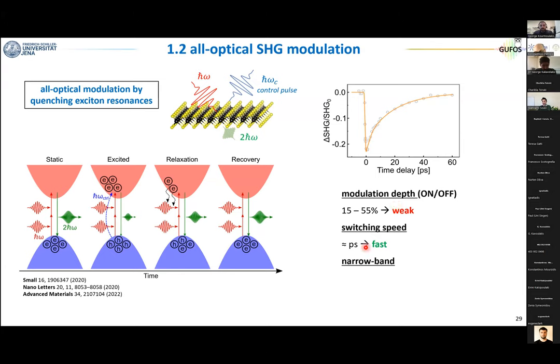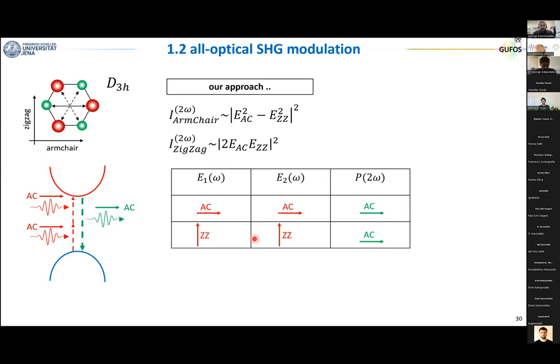But there is another big disadvantage, that this method is now very narrow band. So this method only works if your fundamental beam or your second harmonic is at resonance with the exciton. Otherwise, you cannot have any quenching. And this is where we came with our idea, where we thought, okay, is there a way of combining the best of the two approaches? So very large modulation depth and very high speed with an ultra broadband bandwidth. And this is possible, and our idea was to do it using the symmetry of the materials.